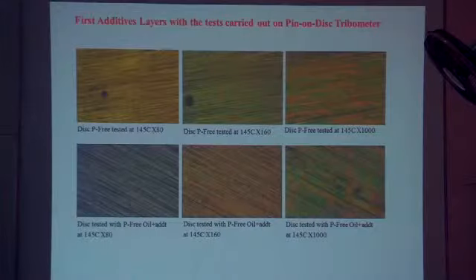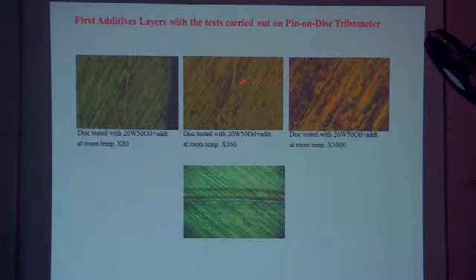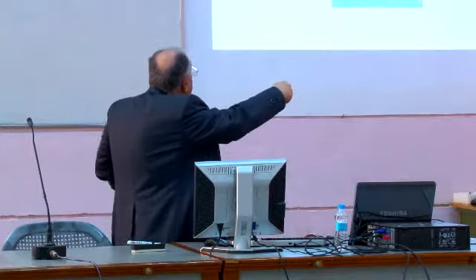What I would like to inform you here is about the disk surface, because the pin material is different from the disk material. The pin material is a steel, and the disk material is also steel, but the disk material has much more chromium in its composition. So at that time, and other times, the layers mostly formed on the surface of the pin, but not on the plate. Maybe I'll show you here - you see this is the disk surface, and in a very small part, I could investigate where layers formed like islands on the surface. There is some, but not too much.